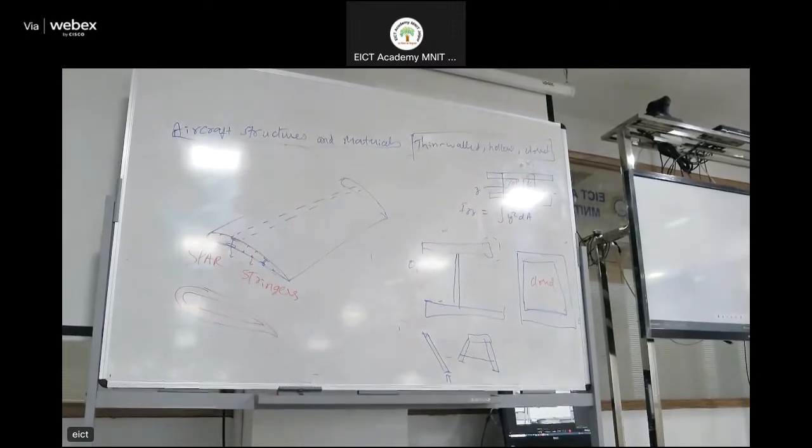Of course, it doesn't always work, right? So the assumption is, once one panel breaks off, then we can replace it. There are certain cases where, in one particular classic case, again, you can look it up, something called the Aloha Airlines incident in the 1980s. What happened is there were small cracks in each of these panels. Each of these cracks were small enough that they said this individual crack won't grow into failure immediately, so let's fly with this. But then all those cracks linked up. They all linked up. And suddenly, midair, one part of the fuselage just flew off.